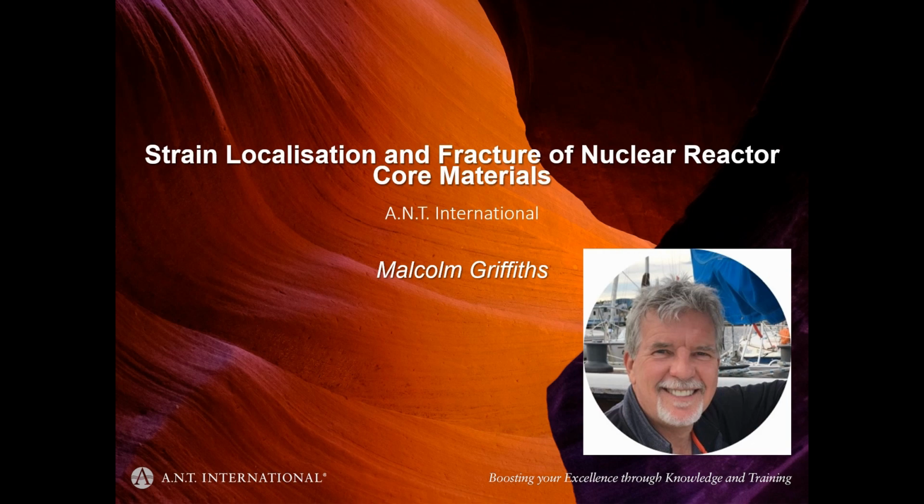But at the same time, people like me were saying to everybody else, if you calculate how much helium is in this material, it's 20,000 atomic parts per million. At that time, we're now up to about 30,000 atomic parts per million, and the materials are still degrading and failing in a very brittle manner. So it behooved me at that time to look into it.